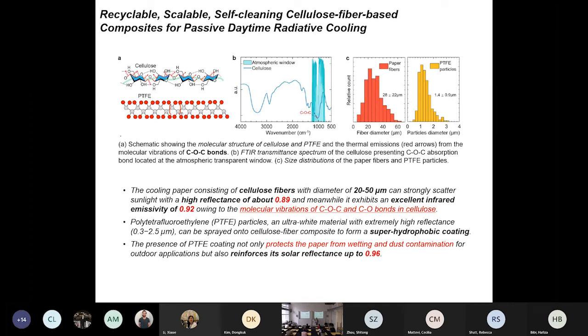And this material, cellulose fibers, is friendly to the environment, unlike chemicals. The paints are chemicals that are toxic to the environment. We also found that cellulose fibers could achieve a high emittance of up to 92%, 0.92. It's still not perfect like 99%, but it's not bad at all. 89% solar reflectance with 92% infrared emittance is actually good for this material.